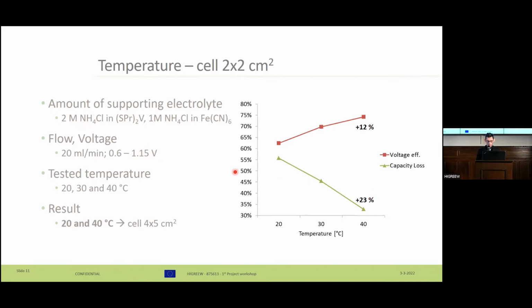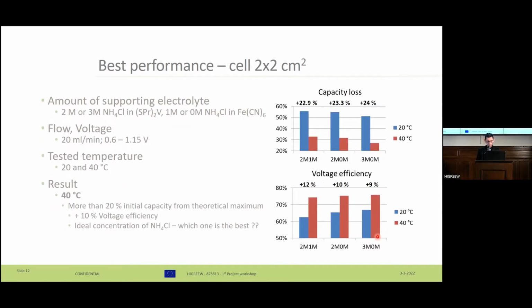So from this data, we get that it might be useful to raise the temperature for another experiment. Another data from the smallest cell, these are combinations of concentration of supporting electrolyte, and the data were almost the same. So bigger temperature means bigger capacity and better values of voltage efficiency.